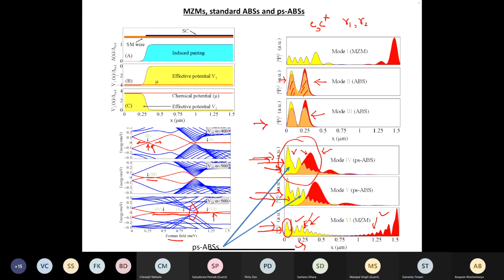Yes, that is true. But the problem with the STM measurement is to delineate the surface or edge state from the bulk state. It is not that trivial. So whether it is the zero energy gap or the peak we're seeing, how do you really claim it is the surface state or the edge state? STM is the champion measurement, but there could be some question marks there also.